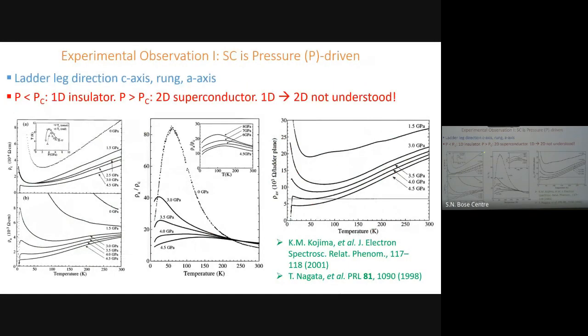So this is the resistance in the C direction. That's the leg direction. And you can see at ambient pressure, it's actually semiconducting, it goes up. Quick, apply pressure, only at 3.5 gigapascal, it becomes superconducting. In the wrong direction, it's even worse. It doesn't come down at all with temperature. It goes up right away. It's sort of incoherent resistance right from the get-go.